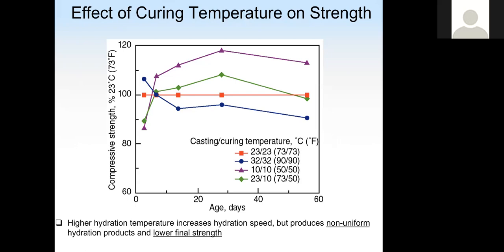Okay. So the reason for that is when we increase the hydration temperature, the hydration rate will increase. So at early age, we have more hydration product. As a result, the strength will be higher. On the other hand, when we have faster chemical reaction, the hydration product tends to be less uniform. We have less homogeneous hydration product. So that will result in lower final strength.